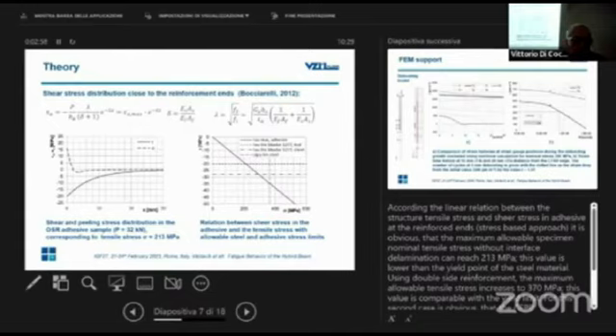We have also calculated this using stress-based approach, this maximum allowable shear stress and peeling stress on the end of the CFRP plate, and for 20 megapascal allowable shear strength in the adhesive, the normal stress on the profiles can be only 213 megapascals, which is lower value than the yield limit of the material. But when we put these plates from both sides, then the allowable limit increases to approximately the yield point of the material.